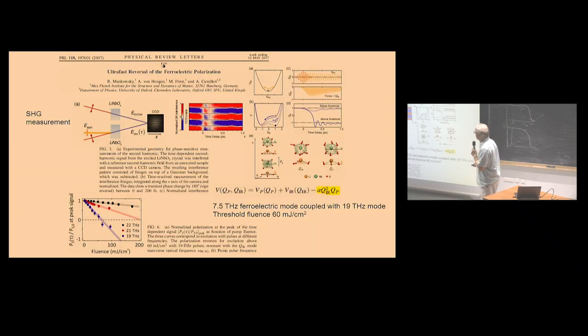And it was similarly confirmed in this paper, also very shortly presented by a speaker last week. In this case, this group, again Cavalleri's group, pumped lithium niobate, which is a good ferroelectric, and they measured second harmonic generation. You know already what second harmonic generation is; we had a talk about it. This blue and red correspond to polarization up and down.